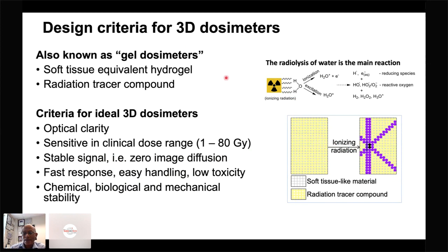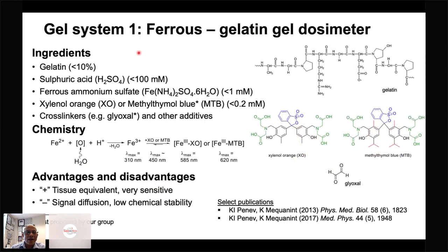So these are basically the design criteria that we have, and moving forward, we started with two different gel forming materials. The first one is iron gelatin combination, and so we used the gelatin less than 10%. And then we have other additives in here. Xylenol orange was added just as a color forming compound to form a complex. When iron 2 is converted into iron 3, that's where the image is actually formed.